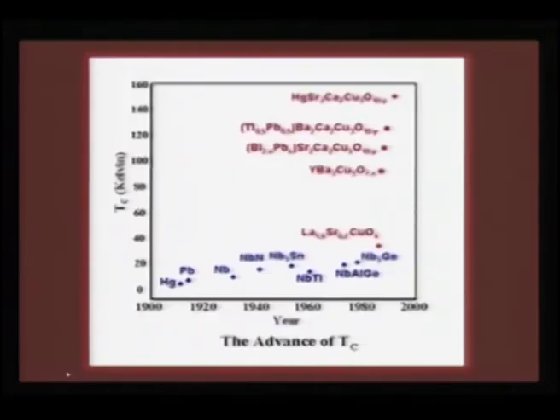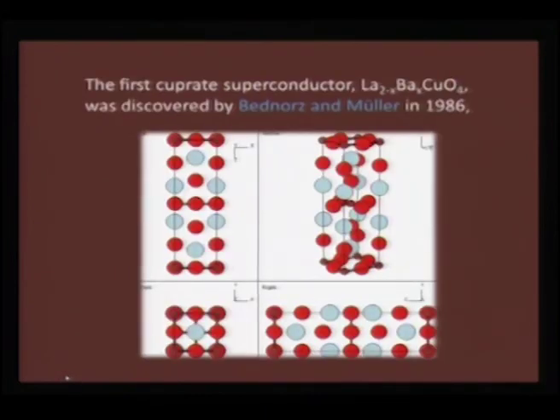If you plot years versus Tc in Kelvin from the previous table, you would see that there are two plateaus. One, with all the metals, where a marginal increase has been achieved, and then from 1986 onwards you see a phenomenal jump in the Tc. So, there are two plateaus for this range of compounds. One has to do with the metallics, and then you see the skyrocketing influence of the cuprates in increasing the high Tc.